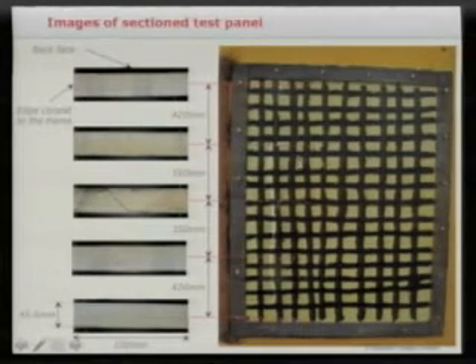And you can see you've got these cracks running down from one skin. This is the glass fiber skin on one side, down to the glass fiber skin on the other side, and these are running down at 45 degrees. So we've got a combination of shear cracks, and we've got some delamination. Well, we didn't fail that sample over there. We did that intentionally. In fact, the machine didn't quite have the capacity to fail the sample, but we are going to fail the next one.